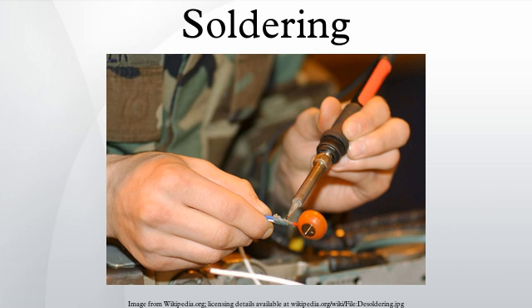With a solder ring joint, the joint is heated until a ring of molten solder is visible around the edge of the fitting and allowed to cool. Of the three methods of connecting copper tubing, solder connections require the most skill, but soldering copper is a very reliable process, provided some basic conditions are met. The tubing and fittings must be clean to bare metal with no tarnish, any pressure which is formed by heating of the tubing must have an outlet, and the joint must be dry.